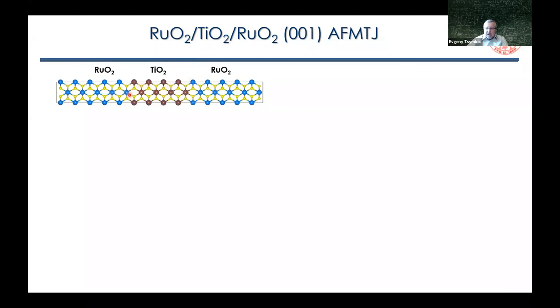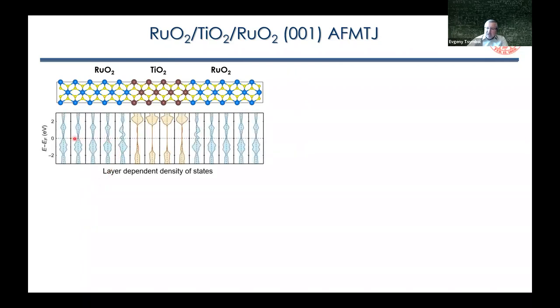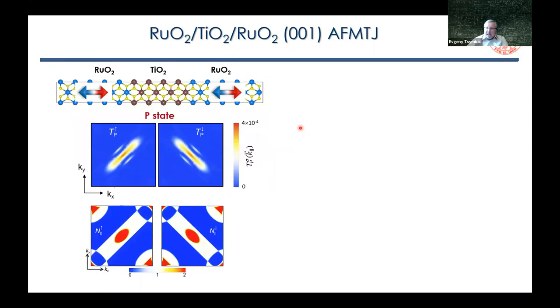So we can potentially grow the epitaxial antiferromagnetic tunnel junction and potentially measure this tunneling magnetoresistance effect. Now, if you compute the electronic band structure, we see that the Fermi energy is nicely positioned in the band gap of titanium oxide. So we should have a tunneling process if we compute conductance using this idea. Let us first show what happens if you have parallel aligned Néel vectors. What I'm showing here is the calculated transmission in the two-dimensional Brillouin zone.